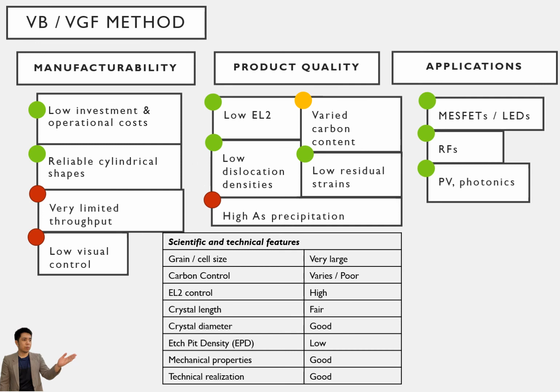In summary, VB and VGF methods are very similar with each other, except for their manner of cooling or solidifying gallium arsenide. This results in overall low capital expenses and good quality product, however at the expense of throughput. Both methods, when compared to LEC, are mostly influenced by the grain or cell sizes. It results in low EL2 defects and low residual strains, forming a good candidate for high-end electronic products.